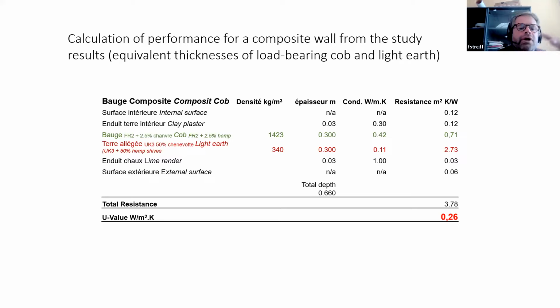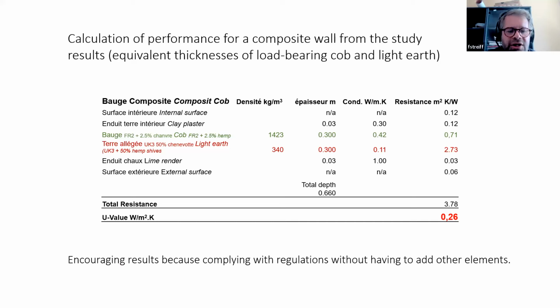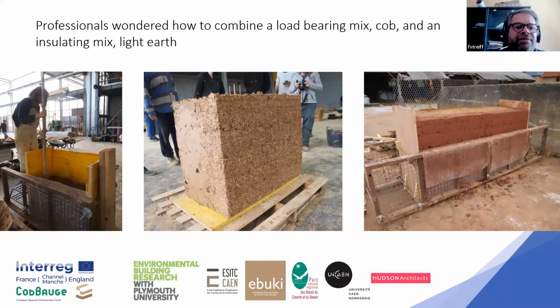So within that sort of theoretical calculation, we managed to see that with a wall of 60 centimeters thick, 30 centimeters of cob, 30 centimeters of light earth, we managed to have a thermal resistance of 3.8, so a U value of 0.26, which allows us to meet the English thermal regulation and helps us in the French regulation to meet the performance that is required. So something really, really encouraging, which pushes us to go deeper in the building process.